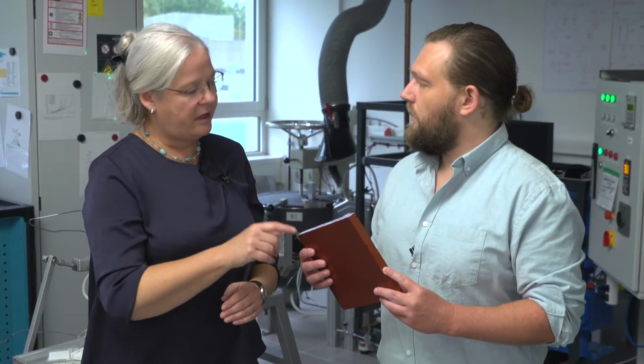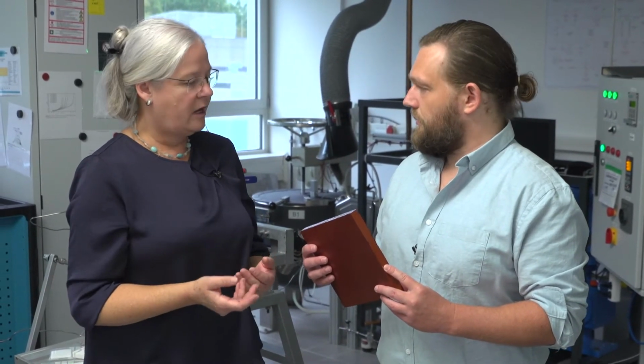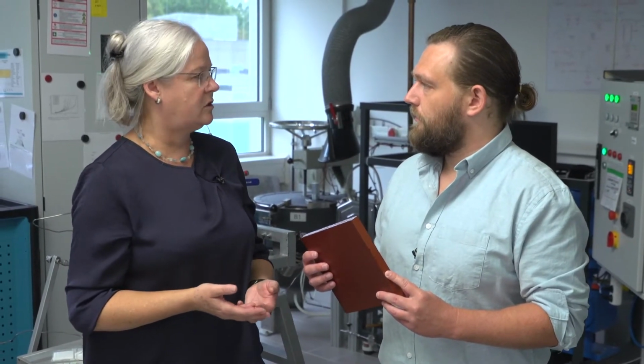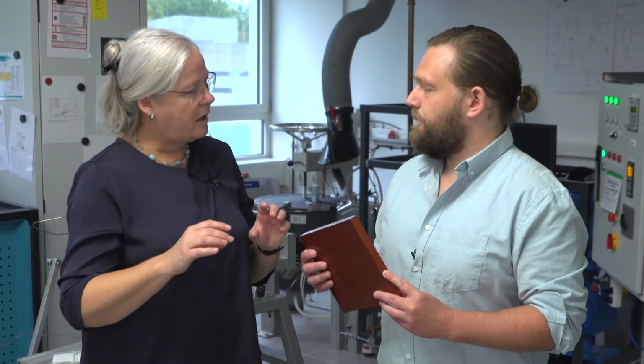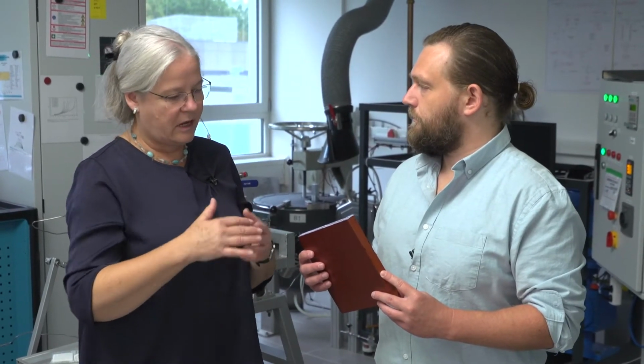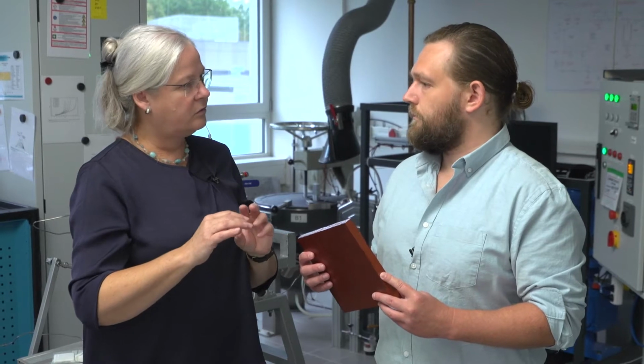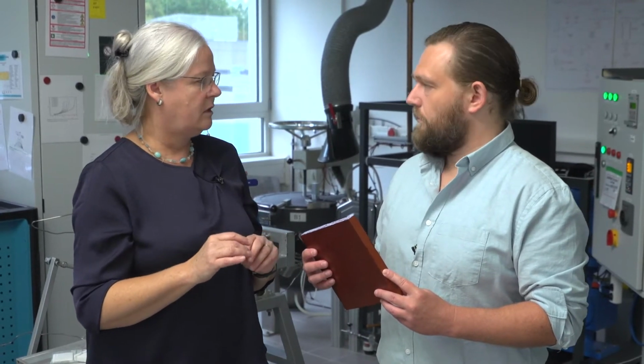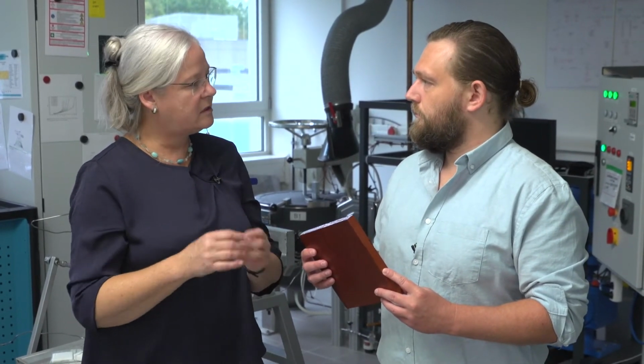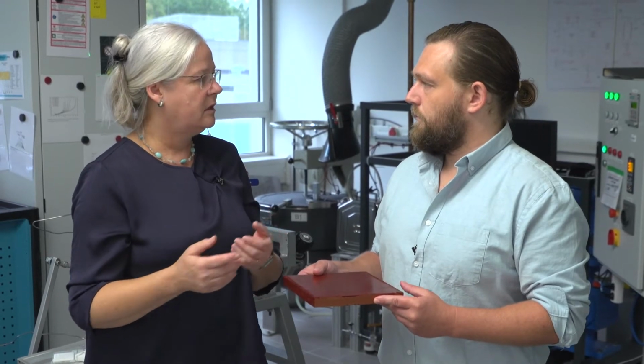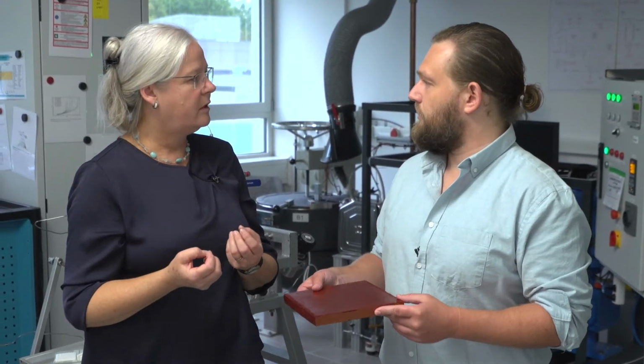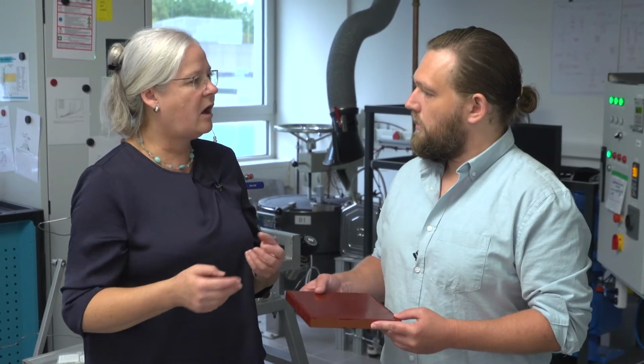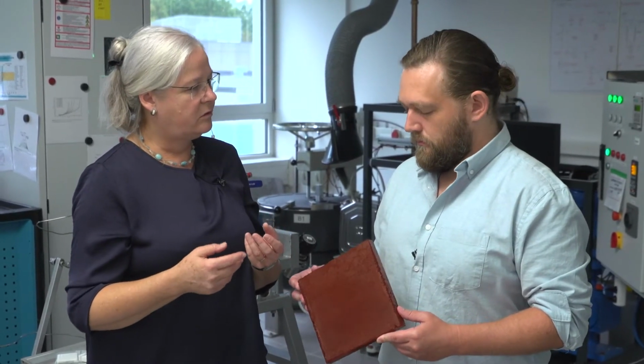But they have a huge inner surface, and we can pyrolyze them, and we get the carbon out of it. Cool. And this material we use for foundry applications. So we have the cast parts and all cuts inside. We have to use sand cores. And then we use this material inside the sand cores just a little bit, like an additive, and we absorb all these gases coming out of the material during casting.